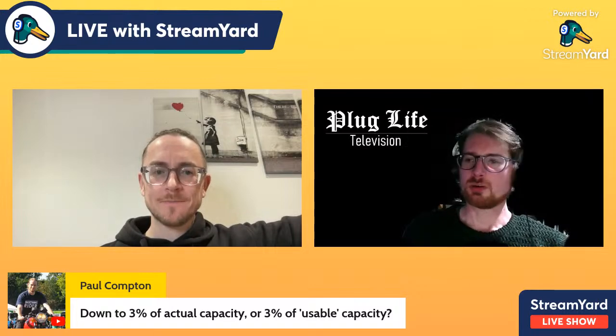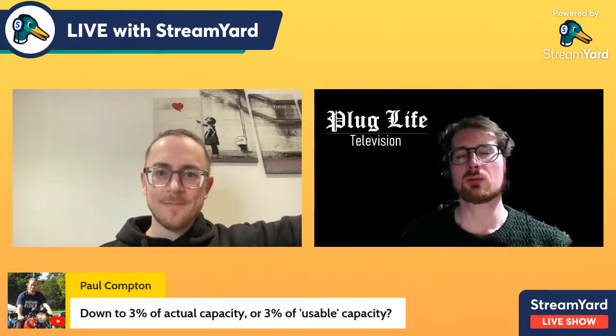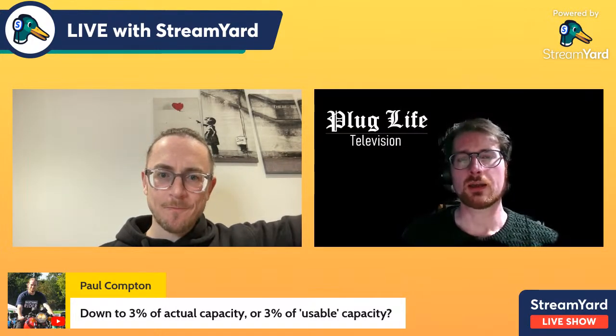Good question from Paul. Actual capacity versus usable capacity. This is very much dependent on the EV. Absolutely, because the state of charge buffers that you find in a BMS are very different from EV to EV. You look at the 30 kilowatt hour Nissan Leaf, it was notorious because its buffers were too small. So the ones where one careful old lady owner leaves it charging to 100%, takes it down Tesco's 5 miles and back once a week, and then plugs it in again, is just waterboarding it to death with electrons. To be fair, also the BMS was incredibly pessimistic about the state of its battery. So there was a software update that corrected that. So you miraculously regained capacity. It was just a bit pessimistic about its true state of health.